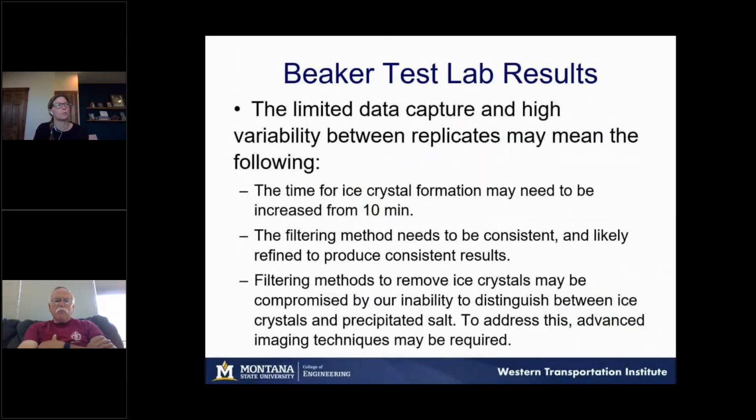So what are the takeaways from the beaker test? Unfortunately, it was challenging, as all lab and field testing are. There was some limited data capture at certain temperatures in terms of being able to capture these ice crystals and capture the high resolution images of them. In the future, if this was done again, we would increase the time for ice crystal formation from 10 minutes probably to 30 minutes. Again, because of the different time lengths, some of the ice crystals were very small, and so different filtration methods were used, and this may have led to some inconsistency.